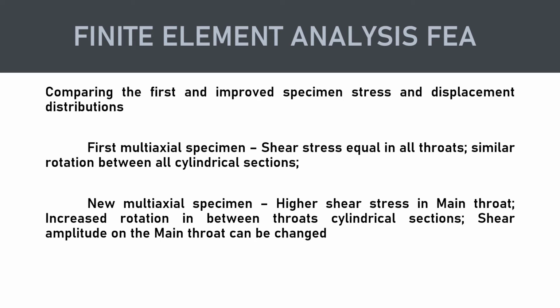Now the first specimen geometry follows certain rules. These rules resulted in the equal shear stress between all three throats, and this was the result of a similar rotation between each cylindrical section. Now, by manipulating the geometry, we were able to increase rotation between cylindrical sections, and thus we can achieve a higher shear amplitude in the main throat that can be manipulated and can be changed to our desire.